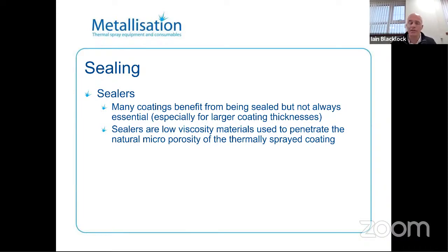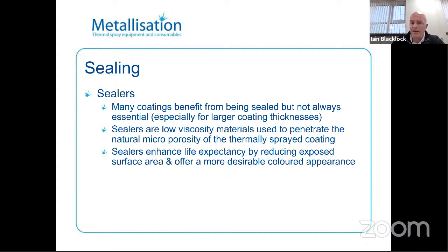The porosity in the coating isn't like a paint bubble, it's micro porosity. So when you apply the very thin sealer onto the surface, it sucks into the coating like a sponge and it seals off all of that porosity. So what that does is it enhances the life expectancy of the coating because it removes the through porosity, and it reduces the exposed surface area. And you can have coloured sealers as well, so it can offer a more desirable coloured appearance to the coating itself.